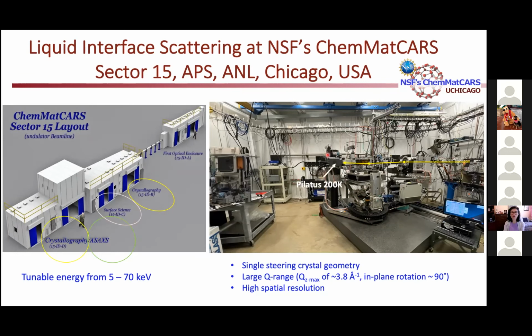We have used the Pilatus 200K detector for reflectivity, for GID, diffuse scattering—all the same detectors. We use Pilatus 1M cadmium telluride for high energy above 20 and 30 keV. We also have a vortex detector, which is the energy dispersive detector for X-ray fluorescence measurement.